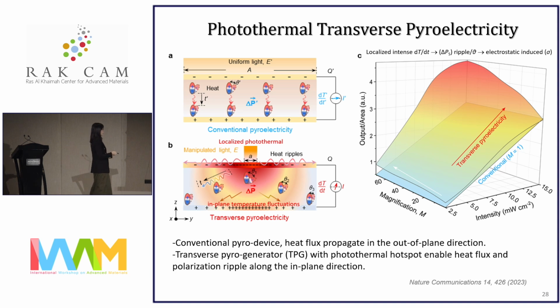And in our design, we have a transverse pyro generator, TPG, with a photothermal hotspot that allows the heat propagation and polarization along the in-plane direction, meaning in the XY direction, a transverse direction. By doing that, we have a localized intense rate of heat variation that allows us to have larger polarization ripples, or larger dipole shifts, attributed to a higher electrostatic induced surface charge density.